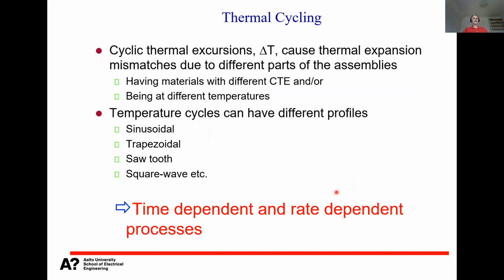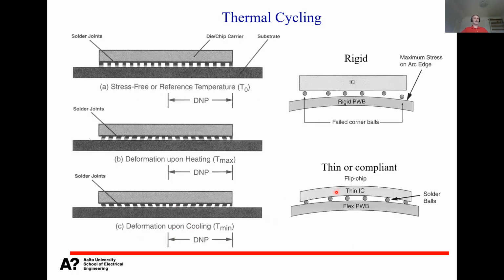And then you have these changes. You have thermal cycling, which means that you are going up and down. Different materials expand to a different extent and at a different rate, and then you produce stresses. And therefore, you have time-dependent and rate-dependent processes, depending on how fast the cycling is happening. So just showing with this one. If you have a component and substrate which expand, they have different CTE, then depending on the size of the component and how much the temperature is changed, these materials, like here it would be solder joints, are stretched.